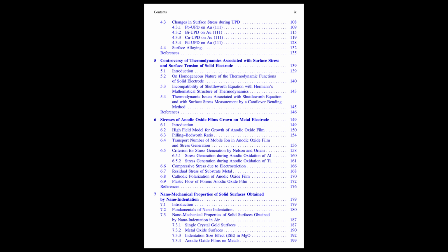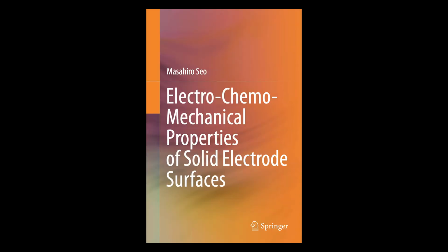Now, you mentioned surface alloying earlier with the lead example. Can we delve into that a bit more? How does that fit in? Sure. Surface alloying, like we saw with lead on gold, is the formation of an alloy that's basically confined just to the outermost atomic layers. What's really intriguing is that these surface alloys can form even between metals that don't mix in their bulk forms. They might be immiscible normally. So you could not make a chunk of this alloy, but right at the surface, their atoms can mingle, like a very exclusive club only existing at the interface. That's a great way to put it.